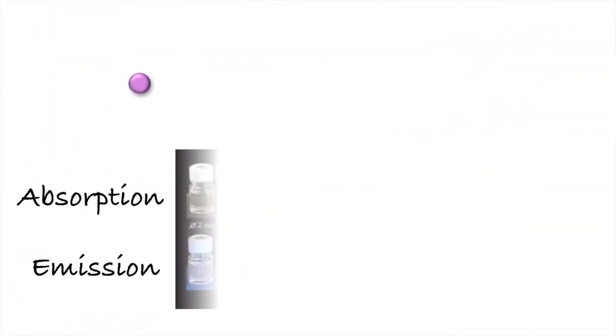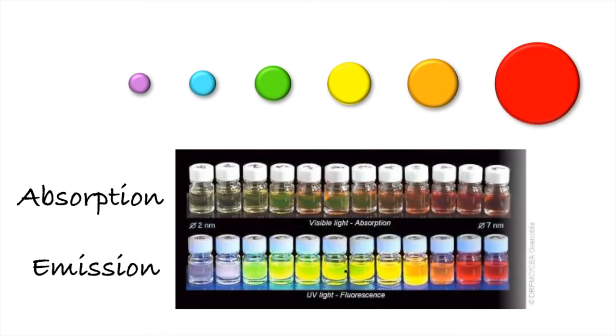The use of semiconductor nanocrystals or quantum dots for energy conversion, in particular solar energy conversion, has exploded in the last few years due to their intense light absorption, bright luminescence, and high stability. Moreover, their absorption and emission properties can be tuned by simple variations of the size to cover different regions of the spectrum.